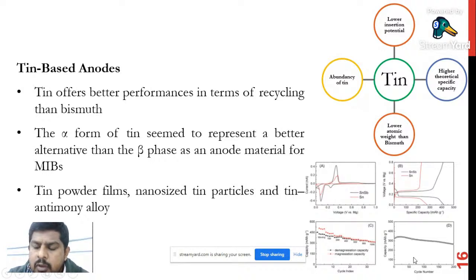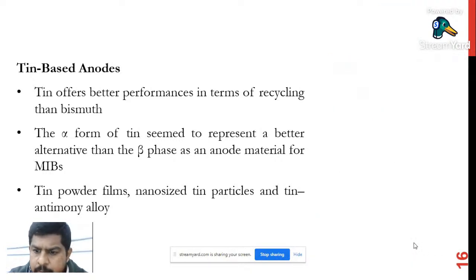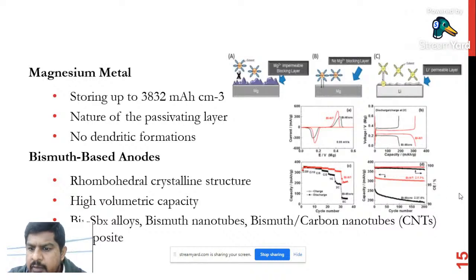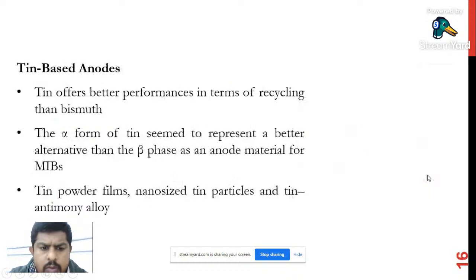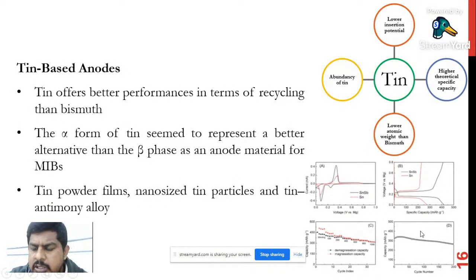Okay, and if you run it for more than 200 cycles also, it is not fading very fast. It is okay when we compare with bismuth. If you compare with this bismuth, you see the cycle is getting very fast. It is getting very fast here. So here in the tin, it's a gradual reduction. So tin plays a major role in anodes of magnesium ion batteries.